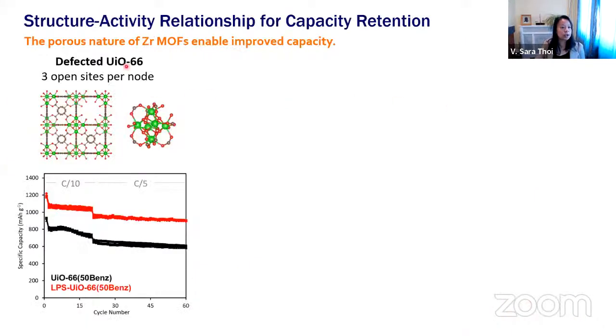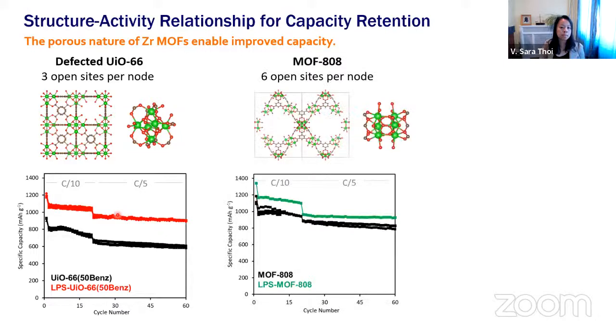When we did this, we saw that using the UiO-66 model, where we have 3 open zirconium sites to accommodate 3 LPS units, we indeed see very large increases in our specific capacity that indicates that we get better sulfur access and utilization. And even more importantly, from cycle to cycle beyond the first cycle, we see relatively stable capacity retention. If we use our MOF 808, which is the same zirconium type cluster, but utilizing a different organic linker that enables 6 open sites for LPS modification, we again see an increase in that capacity as well as very high capacities of retention.